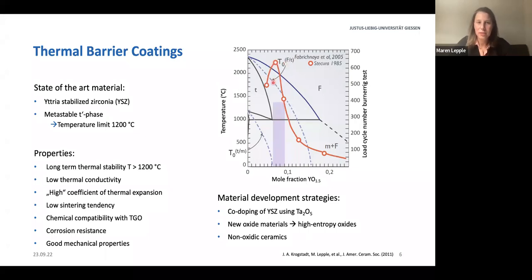But this means that because we have a metastable phase, we also have a temperature limit for long-term operation of around 1200 degrees centigrade. If you go to higher temperatures, this metastable T prime phase will decompose to the equilibrium phases, which are the tetragonal and the fluorite phase. And so they are not favorable. So they do not have these good mechanical properties. And during cooling or during the thermal cycling, for example, the tetragonal phase will transform to the monoclinic phase. And this has a huge volume expansion.